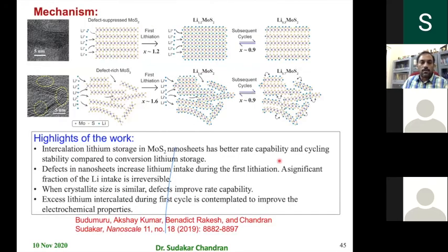In addition, at high C rate you get the cyclability, and the reason the cyclability at high C rate can happen is that the lithium goes onto the defect sites, and the migration of the lithium is facilitated by the lithiums that are trapped at these defect sites. So the excess lithium present in the defect sites on the edges facilitates the improvement in the electrochemical properties.